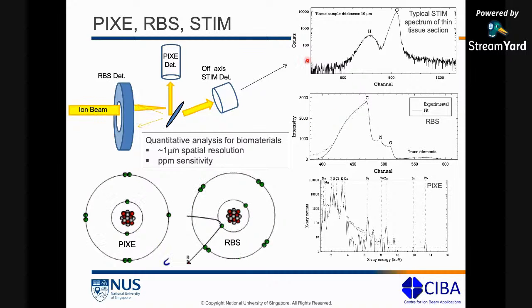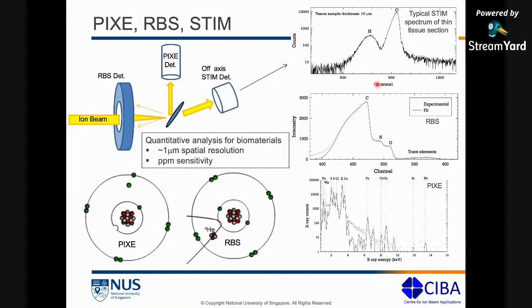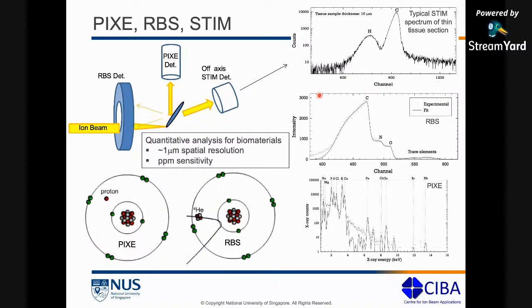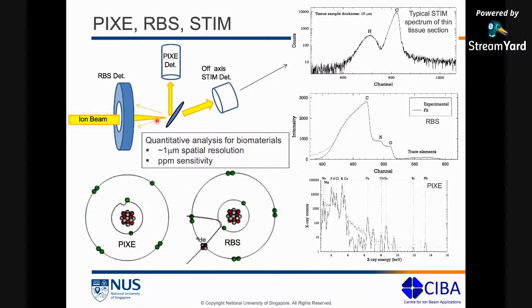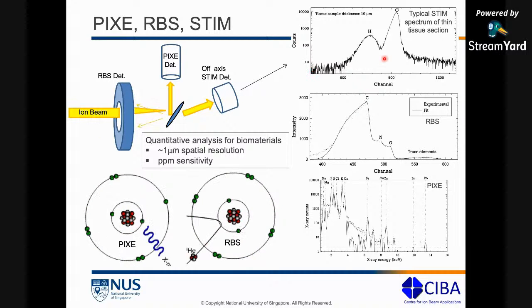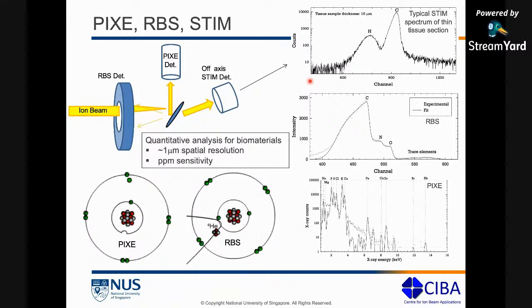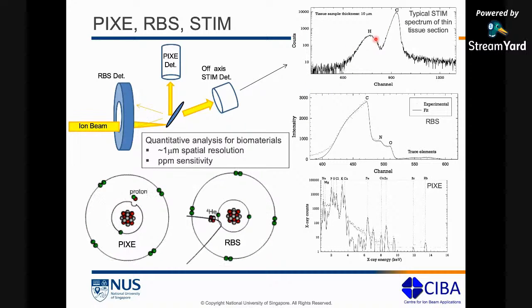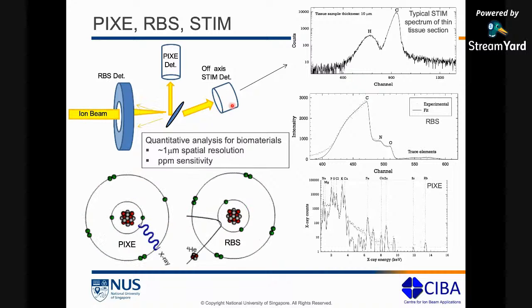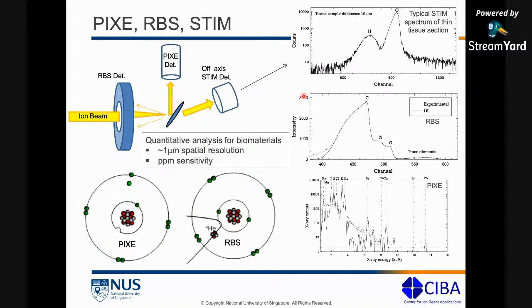And then the STIM spectrum is again counts versus channel, or in this case, again, an energy scale. And in this case, it's the forward scattered ions coming out. So if it's a biological cell, your counts for carbon and hydrogen will be huge, because hydrocarbons are mainly present in cellular structures. So you will have these two predominant peaks of carbon and hydrogen in a forward scattered off-axis STIM spectrum. Carbon being heavier comes out at a higher energy compared to hydrogen. Okay, so these three spectra are typically always collected at the same time.